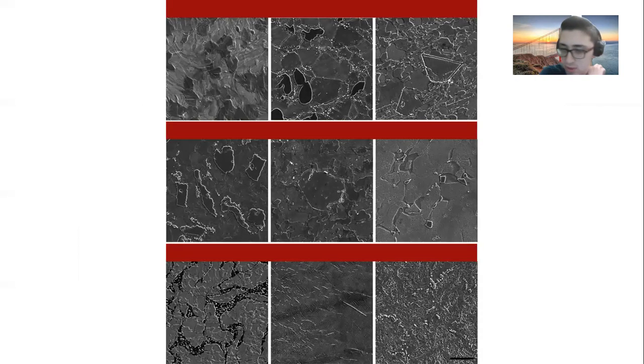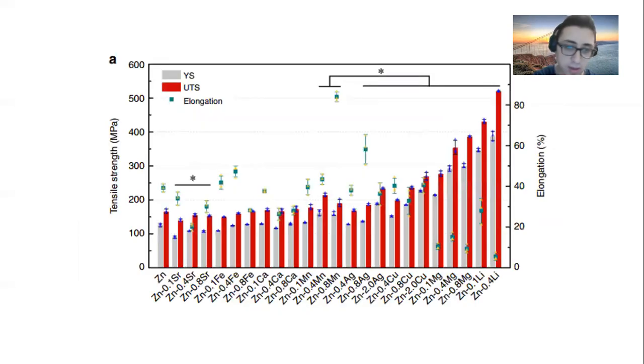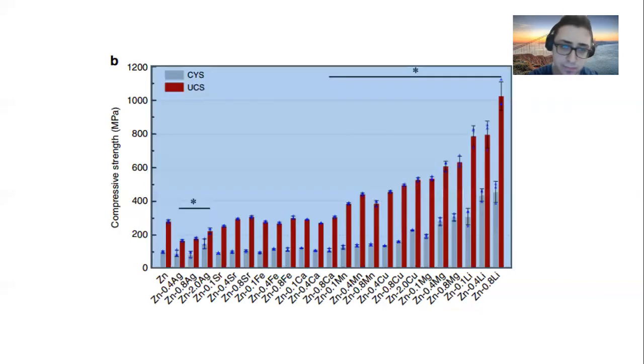These are the microstructures, not very important. These are their tensile strengths. As you can see, this zinc and 0.4 lithium has an ultimate tensile strength of above 500 megapascals. That's really, really good. There are also some very cool elongation values, but we'll get to that later. This is their compressive strength. Of course, there are clearly a lot of good compressive strength values too. Again, lithium is pretty rock solid at that too.